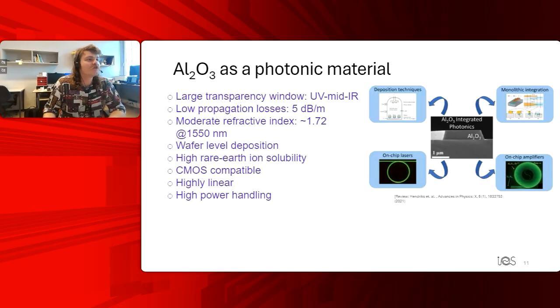A little bit of history on aluminum oxide, a nice review paper you can see written here by the co-founder of Alluvia, Ward Hendricks, that covers a lot of these different transparency windows, whether it's the UV to mid-infrared. It has very low propagation losses. Once you start quoting things in per meter, you know it's good. So this is 5 dB, sometimes we'll see here, as low as 1 dB per meter. A moderate refractive index around 1.72 at 1550.